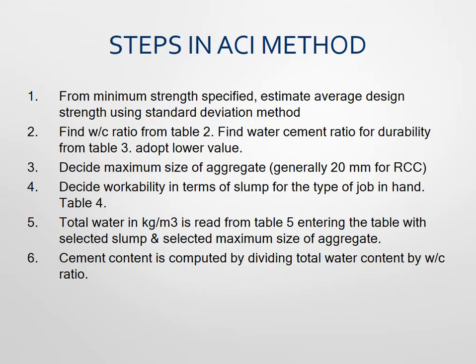The fourth step is to decide the workability in terms of slump. The ACI method refers to workability defined by the slump value, which is decided according to the construction purpose — road construction, building structure, etc. Next, the total water content per meter cube is obtained from Table 5, entering the table with the selected slump and maximum size of aggregate. The cement content is then computed by dividing the total water content by the water-cement ratio.